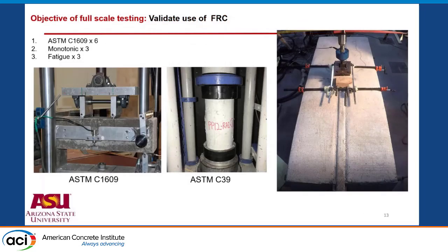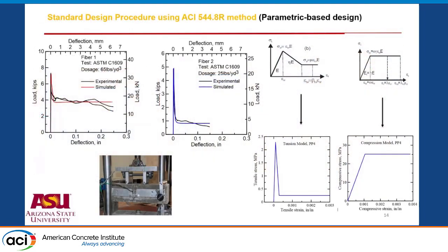Of course, we did the flexural test, ASTM C1609, to measure the material properties, and compressive strength from a QC point of view. The setup is shown here, with the track slab being loaded on the test machine. One of the things that we do with the 1609 test is to document the results in terms of material properties. We back calculate from the flexural load deflection the tensile properties and the compressive properties. Those can be fed into any finite element model or structural analysis model to calculate the contribution of the fibers.